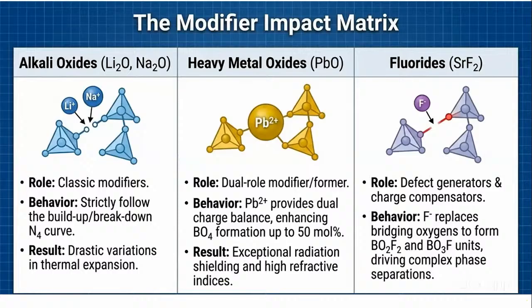But if you're looking at fluorides particularly, these fluorides, they are charge compensators. So what they do is they try to break the oxides and they try to form a separate bond with fluorine over there. So because of this, a defect center is being created within the network. So these defect centers, they play a very crucial role in tailoring the optical properties of these glasses.